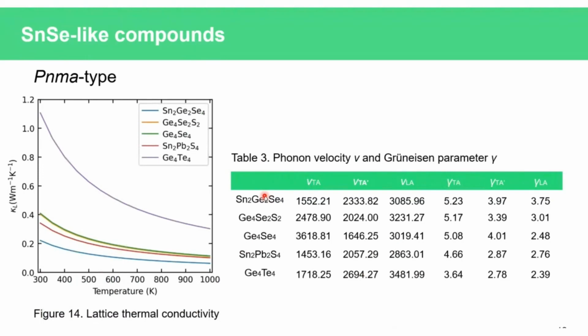However, I found this group of materials have extremely low lattice thermal conductivity. Besides germanium telluride, the lattice thermal conductivity of this compound at 300 Kelvin is already lower than 0.5 watt per meter per Kelvin, close to the amorphous limit.